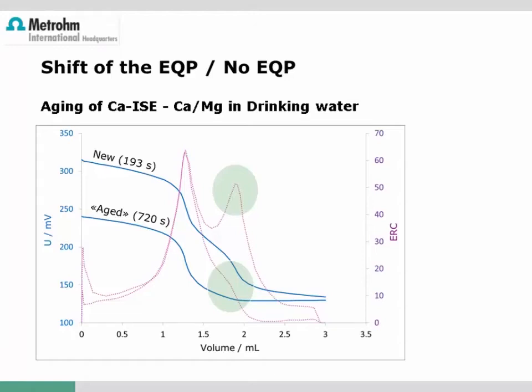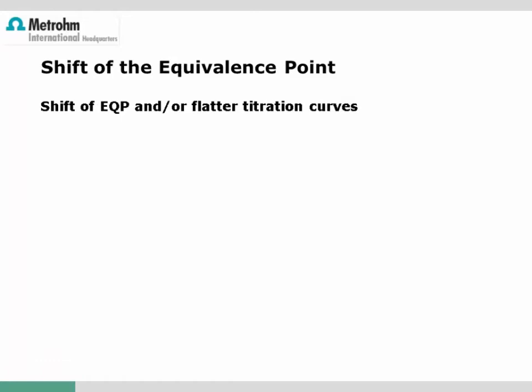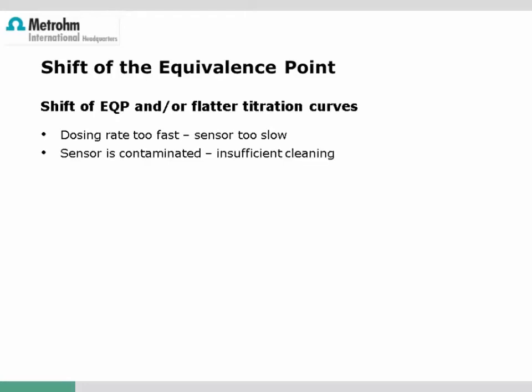So, as you can see, suddenly missing equivalence points are usually easy to explain when looking at the titration curve or a curve overlay. So an instrument or a titration software that enables this can be very helpful. In addition, I hope you have also seen that suddenly missing equivalence points are not necessarily the fault of the instrument itself. Very often, other processes or consumables are responsible for this. This could be, in particular, an inadequate dosing rate in case the sensor has become too slow, or contamination of the sensor, usually a consequence of insufficient cleaning procedures.